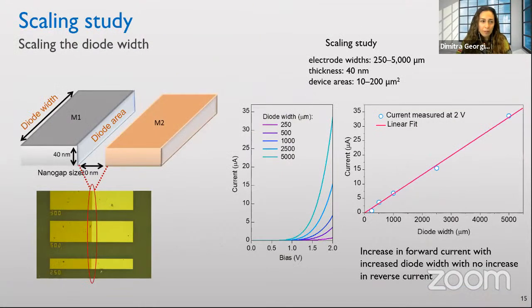Then we did a scaling study, which, as I said, is quite simple to do with this adhesion lithography technique. We changed the diode width. The diode width in this geometry can be easily tuned by changing this part of the electrodes, while in any case we have a channel length of about 10 to 20 nanometers, and the thickness of the electrodes remains the same. So this is the only part that we change. And we see that the current is, as expected, scaling with the diode width. If we scale it from 200 microns to 5 millimeters, we see there is a linear trend. And why is this good? Because in this way we can design our diodes having the exact geometry we want, depending on the output current we want them to have, depending on how we want to use them.